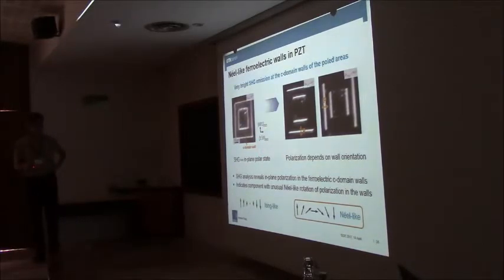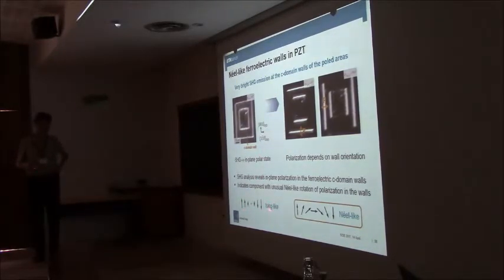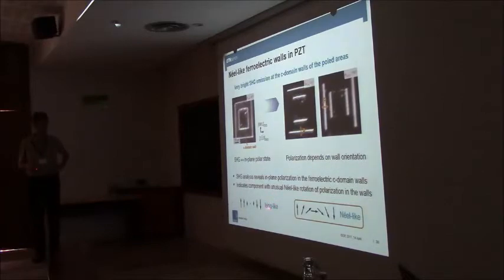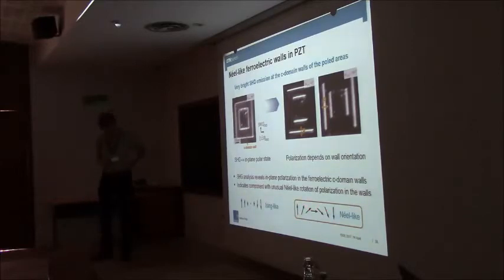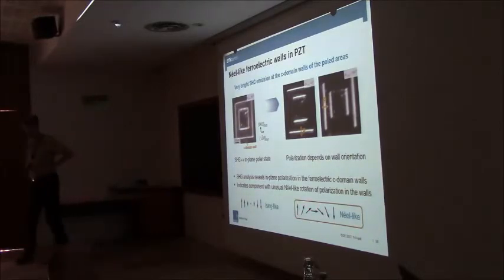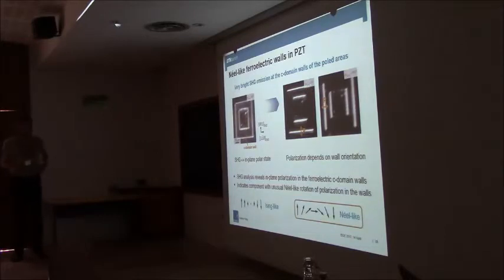So that would, for instance, be possible if, unlike what was suspected first, a domain wall in a ferroelectric really is a transfer Ising-like, so a transfer from purely up polarization to purely down polarization. But maybe it rotates like this, and then you would have an in-plane component, even without having an A domain. So you could have a rotating polarization in your domain wall. That would explain such a signal.